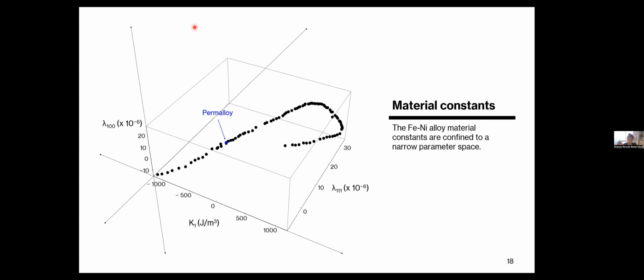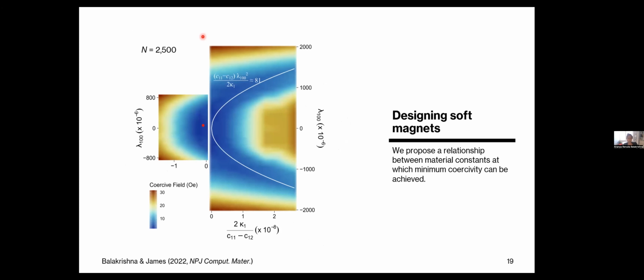So which is what motivated the last part of the work, which is what we call the design of soft magnets. And so what we did in this work was, we ran nearly 2,500 calculations wherein we systematically vary the material constants, kappa 1 and magnetostriction constant. The other material parameters are held constant, just to kind of see the interplay between two material constants to start with. And so what you see is a result of the calculation of over 2,500 simulations. And the way you would read this plot is more like a heat map. And what that shows is that every specific combination of anisotropy constant and magnetostriction constant, there's a specific color. And that color represents what's the coercive field at this specific composition.